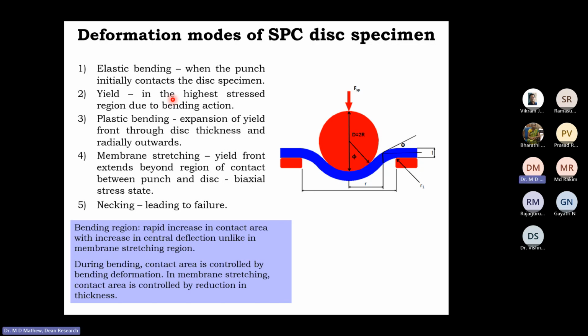So when this bending happens in the bending region, there will be a rapid increase in the contact area with an increase in the central deflection. And the contact area is controlled by the bending deformation. But in the case of membrane stretching, it should be noted that the contact area is controlled by the reduction in thickness.